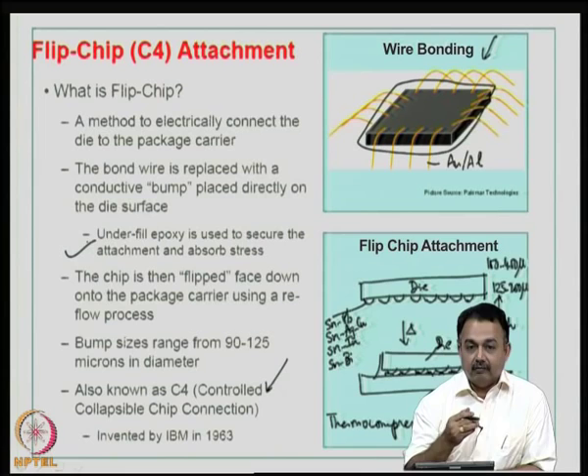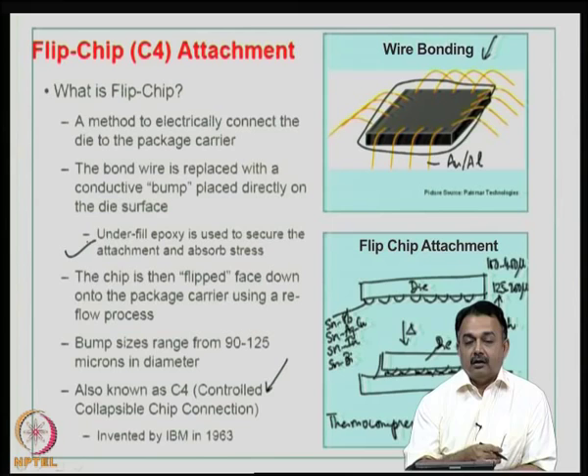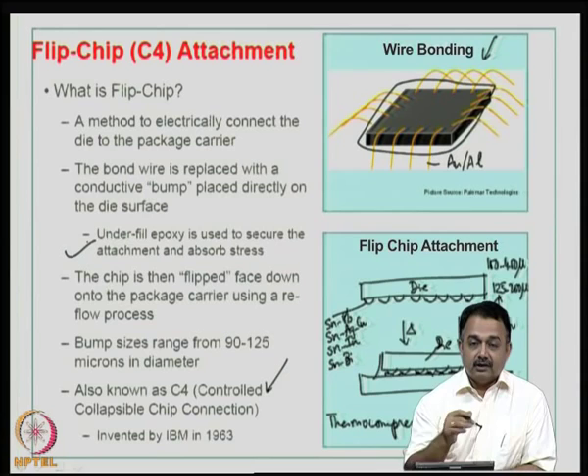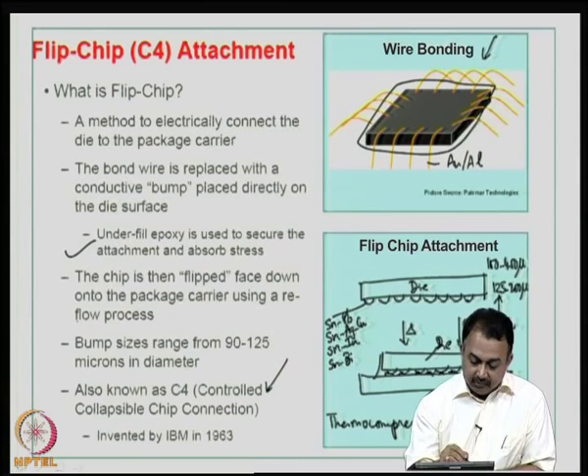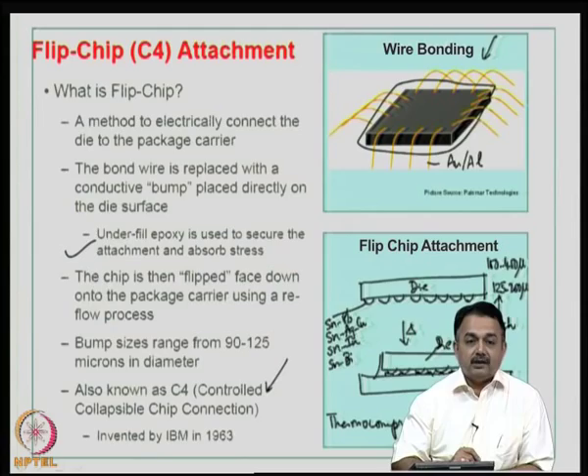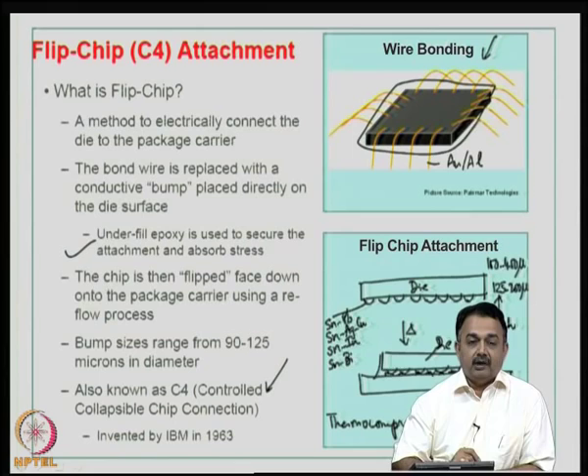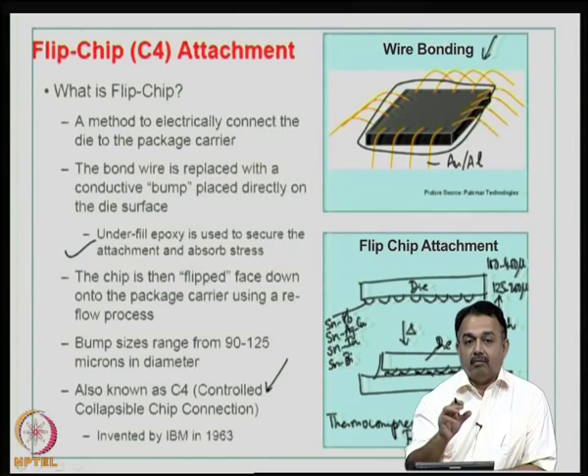There can be heat that comes from the chip which, if accumulated, can crack the die, warp the substrate, and affect the solder joint. The chip is flipped face down using a reflow process. In addition to thermocompression bonding, you can also use a reflow process. Reflow basically means you are going to melt the solder bump again and establish a new metallurgical bond with the bond pad on the substrate. The bump sizes range from 90 to 125 microns in diameter, so you can imagine this is a very high-density connection.